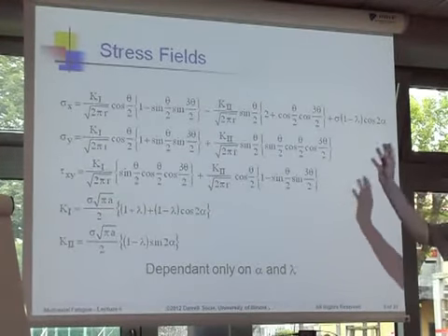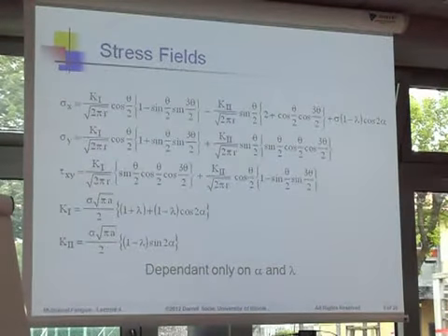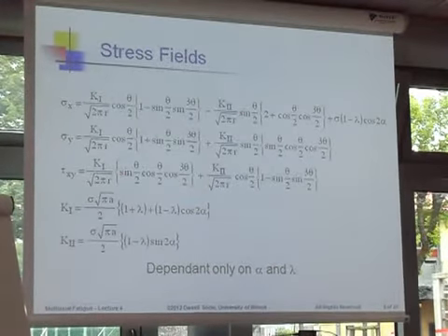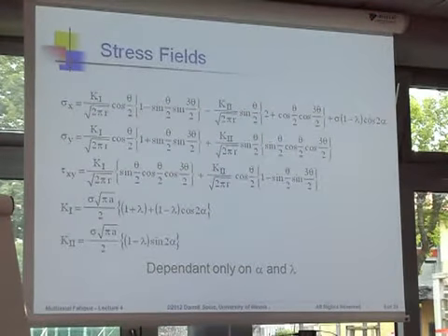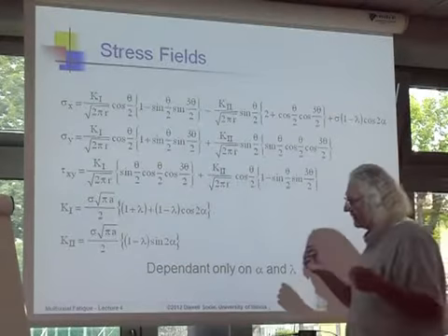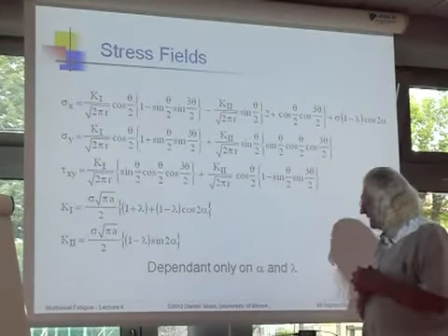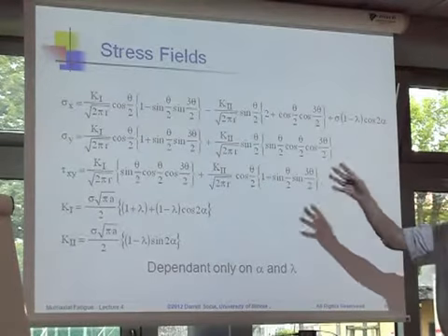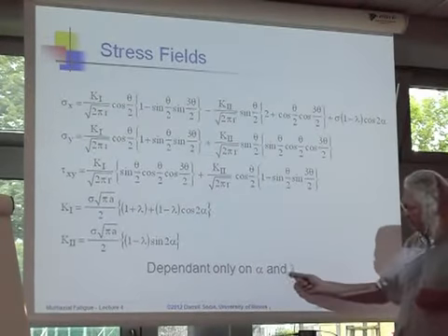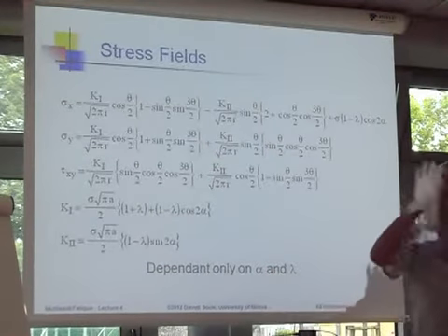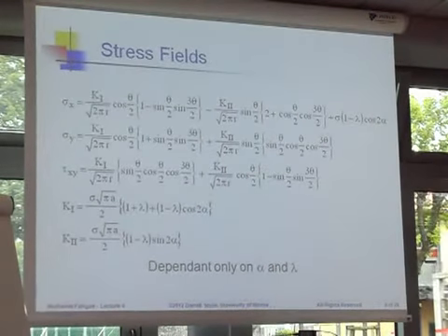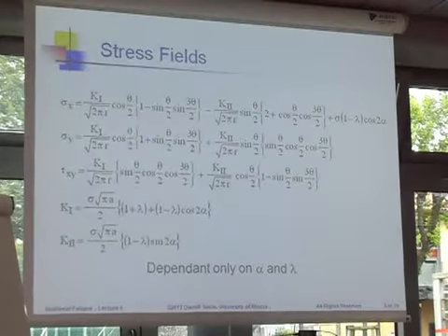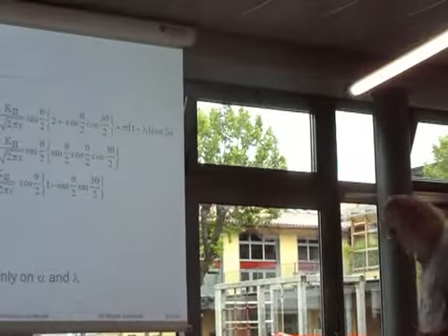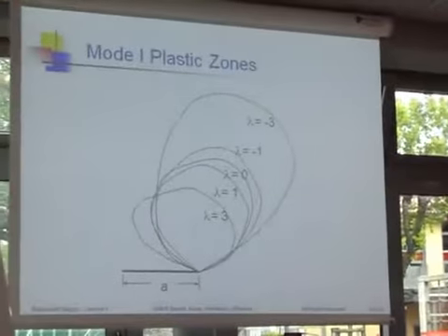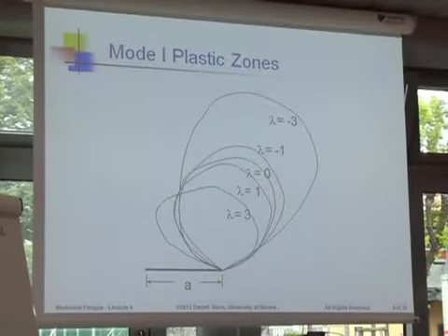But you know, if you look at all of these equations for biaxial loading, they look very much like the standard fracture mechanics equations. For a particular crack that is given the load, and of course you have a crack length, all of the stresses and strain depend only on the ratio of the loads and what the angle of the crack is. Right? Everything else is set by basic fracture mechanics, as it is in a uniaxial loading case of a crack. A uniaxial case of a crack, everything is set by the theory of elasticity equations. Anyway, we just use those and look at the differences in plastic zone.